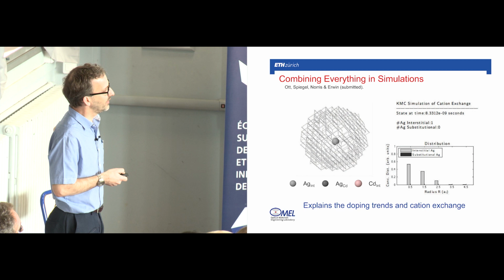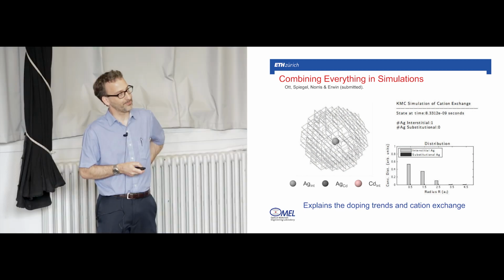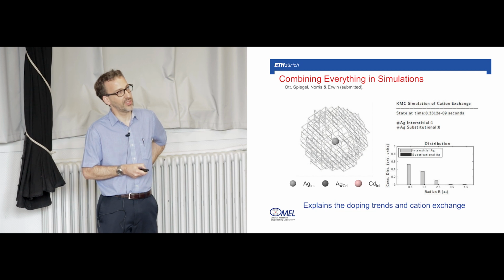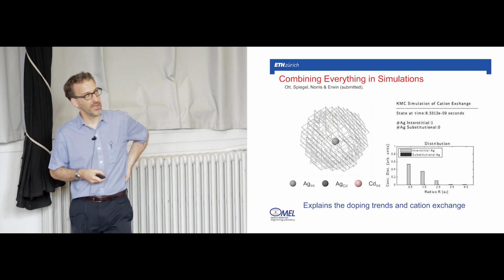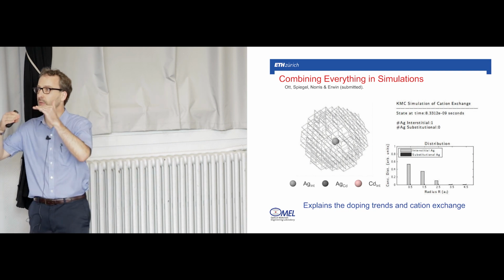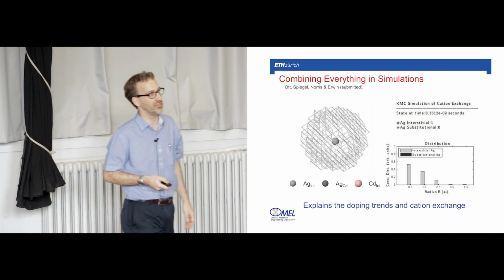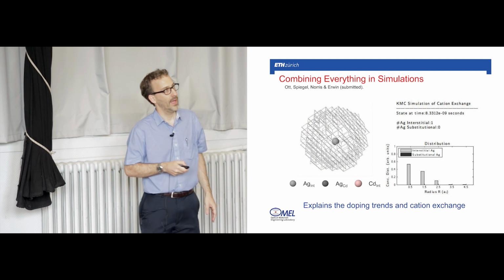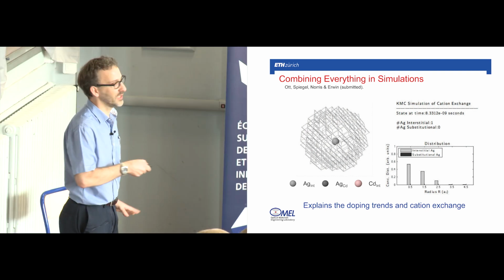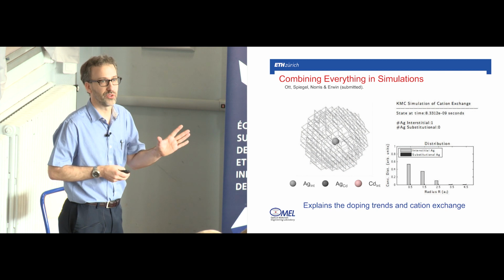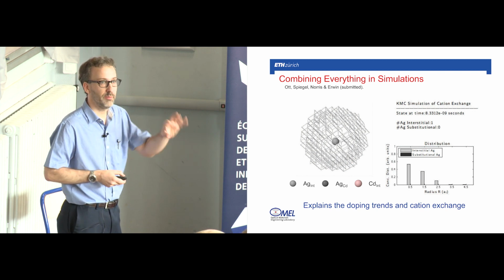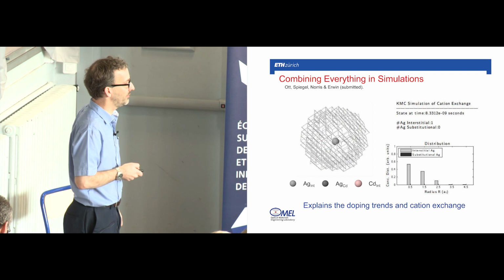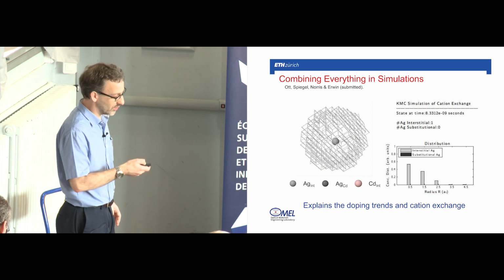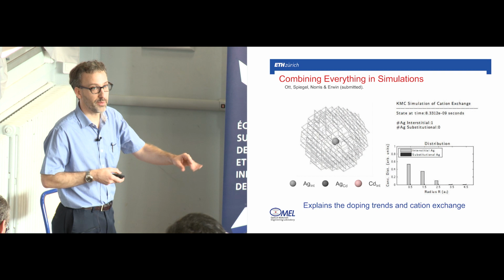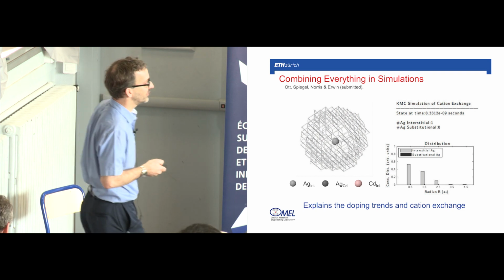By the time the simulation is finished, if we look out here on the surface, this gray line is the number of interstitial silvers, and the dark line is the number of substitutional silvers. These are nearly in balance, which of course is what you would expect from an Ag2Se phase. Now it turns out this simulation that I just showed you will explain all of the results. It'll explain why it's n-type doping at the beginning, because you have these interstitial silvers that are keeping away from each other. And it can also explain why it goes p-type as you get more and more substitutional.